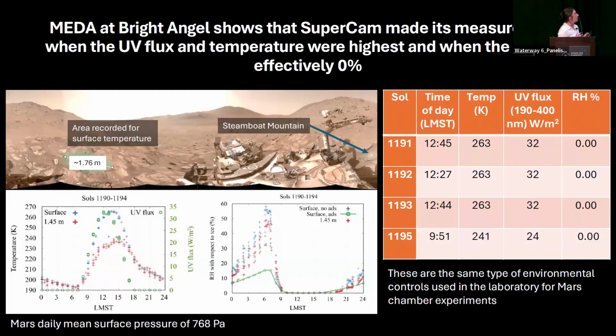All right. So in order to get a sense of the surface and atmospheric interactions happening on Mars, we then paired it and co-located it with MEDA. So using the laser here, we have the temperatures during the times of the experiment, the relative humidity, and the UV radiation fluxes. We're looking at a range of -10 degrees Celsius to -32 degrees Celsius at the time of this abrasion dehydration experiment, also indicating that this is done in the winter of Mars, so it was relatively cold.